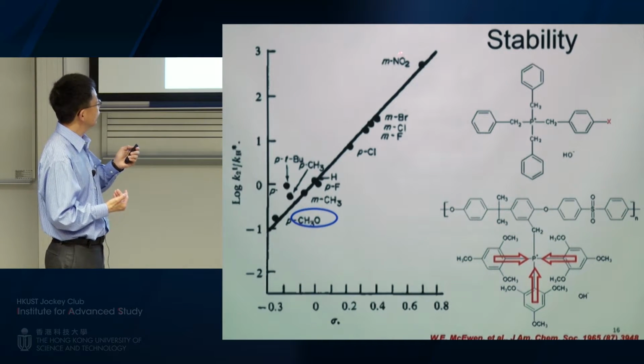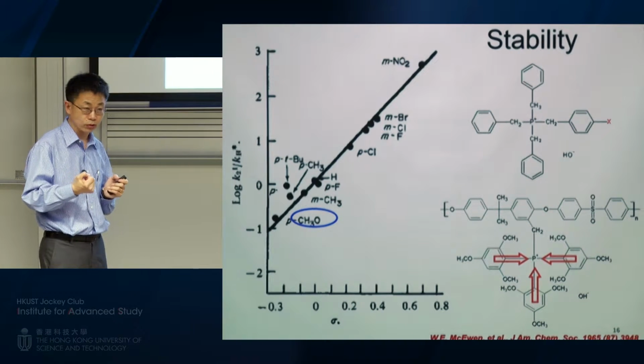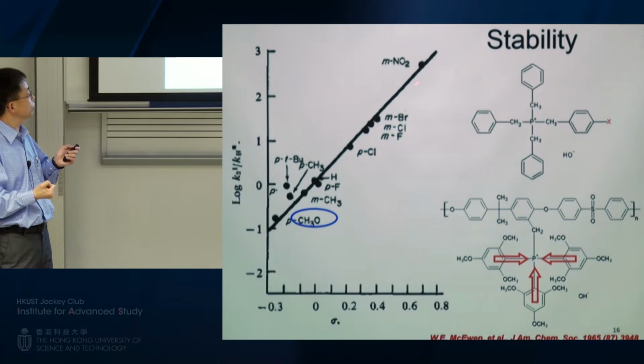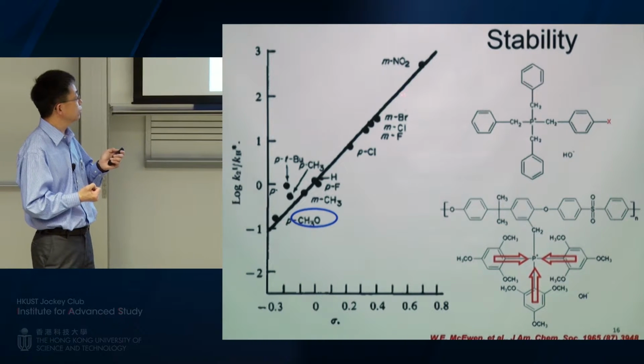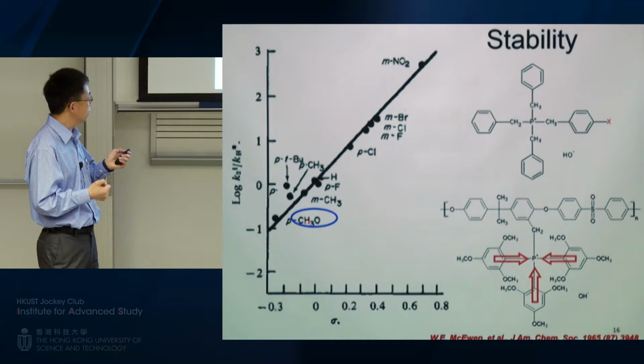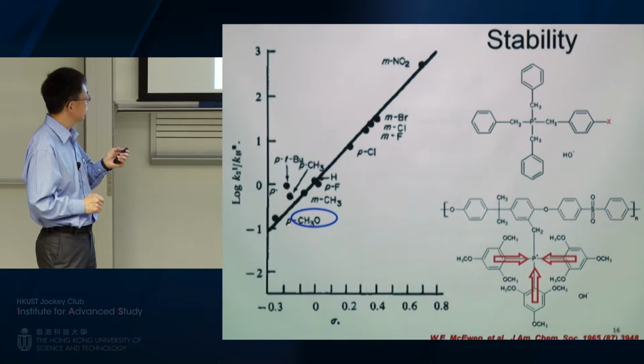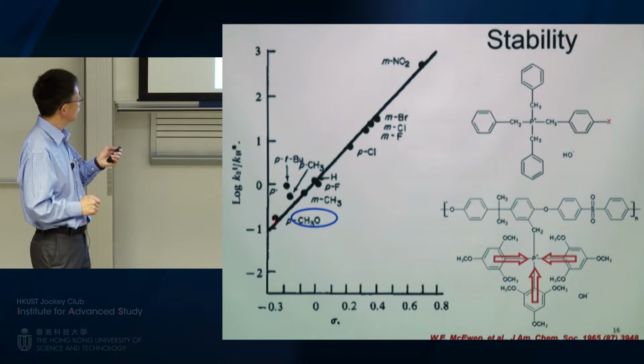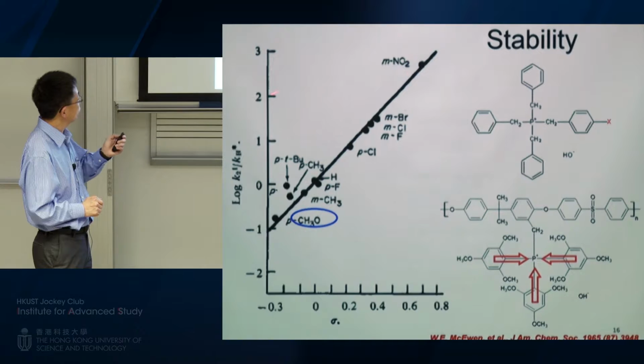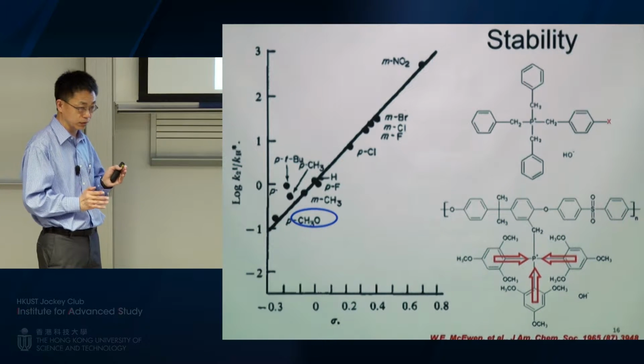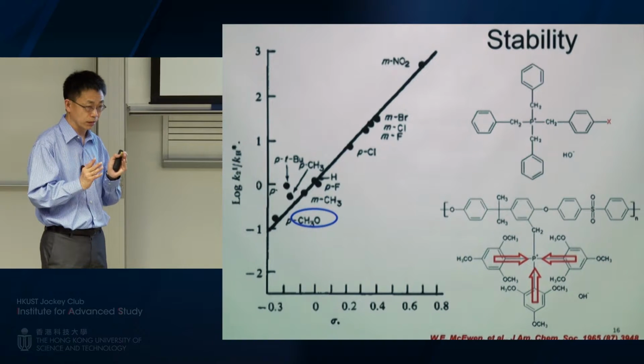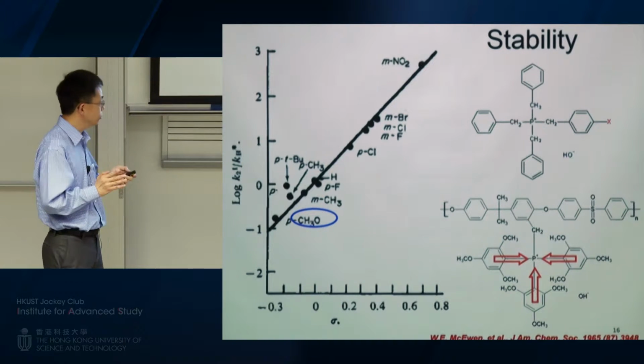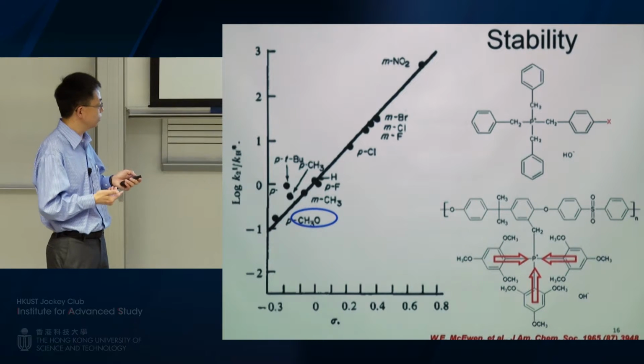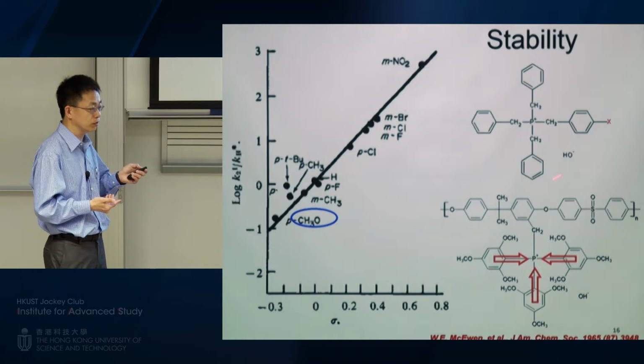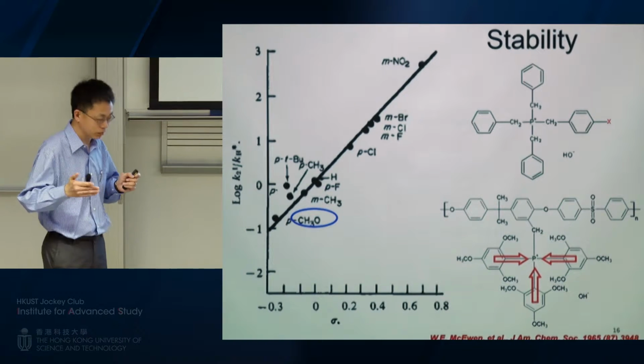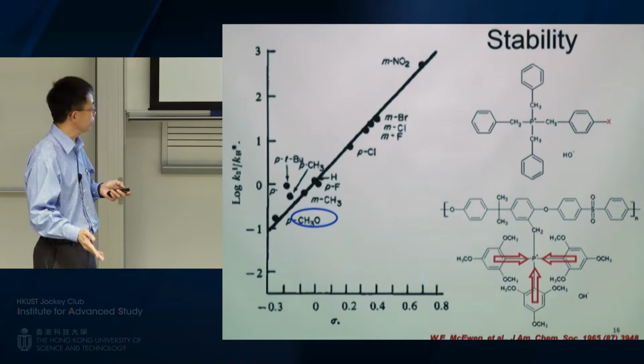So you can see if you have a very, very strong electron withdrawing group, the reaction is very fast. But if you started putting the very, very strong electron donating group like methoxy, you can see the reaction rate is much slower. This is a log plot. So this is about 3 to 4 orders of magnitude of reduction of the reaction rate. So this is telling us methoxy group is very, very critical. So again, our very naive imagination was, well, 1 can do so much for you. What if we put 9? We might be able to really put this one down to the sub-basement.